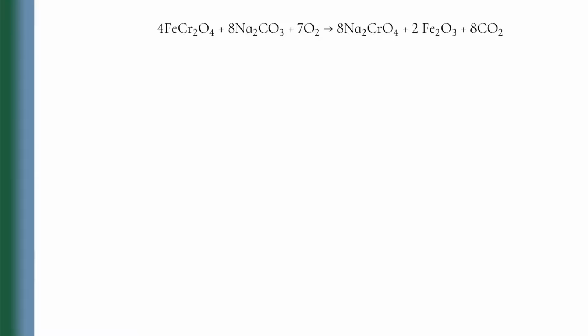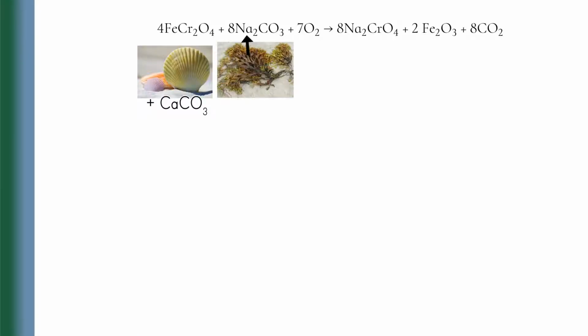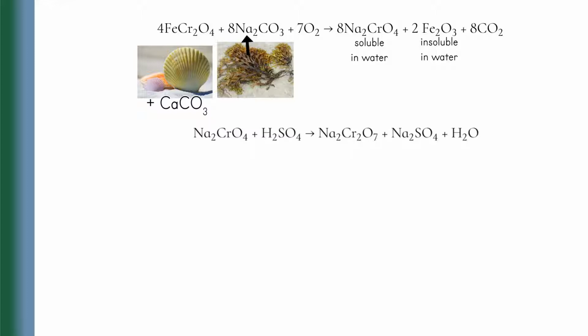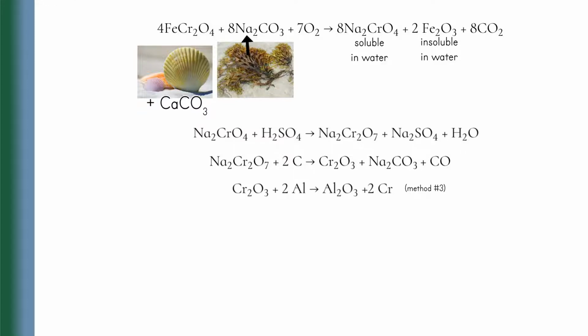Chromite ore is heated with calcium carbonate and sodium carbonate in the presence of air. The chromium is now at oxidation state +6, called chromate, while the iron is at +3. Chromates can dissolve in water while iron oxide doesn't, so now we have separated the iron from chrome 6. The chromate then reacts with sulfuric acid to make dichromate, just a simple acid-base reaction, no redox here. Then, the dichromate is reduced by carbon, probably coal, to make chrome 3. Then, it's reduced further into chrome 0 with, again, aluminum. Looks like the use of aluminum is inevitable here.